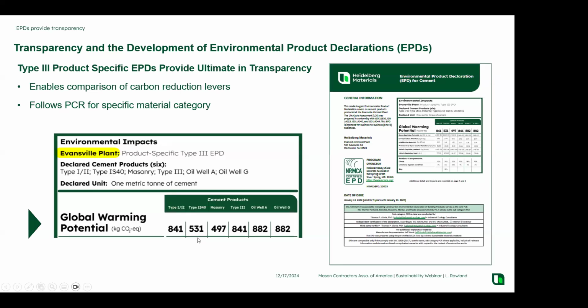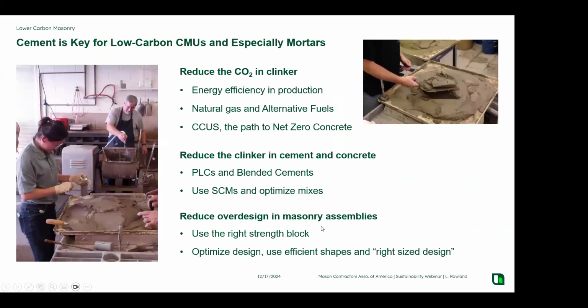This cement helps us every day. Every ton of cement that we sell that is this type 1S40, which is a terrific cement that people really love because it is a pre-blended SCM in with the cement, we're able to reduce our GWP dramatically. So it's a really neat product. And once again, our customers are very much appreciative. Of course, cement, as we said, is key for low carbon CMUs, concrete masonry units, and of course also for mortars, because cement is such an important part in the production of mortars.